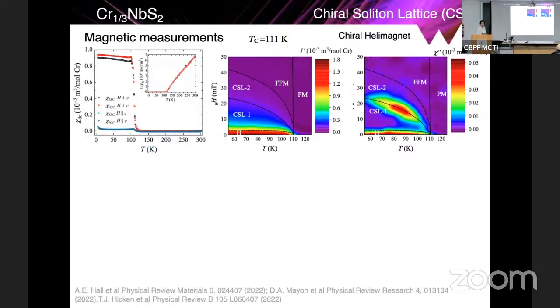Once again, we do AC susceptibility measurements to look at the dynamics in the magnetic susceptibility and plot the HT phase diagram in these. So all these lines, which are drawn as a guide to the eye, are where there is a distinct change in the dynamics that you observe in the AC susceptibility.